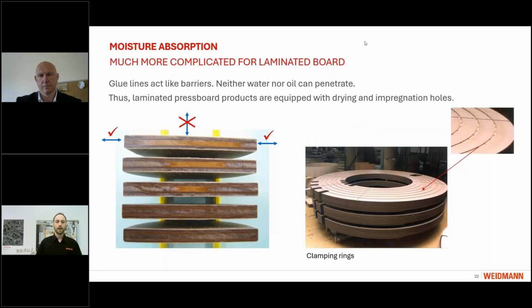Next, we have the glue lines. You know that Weidmann will produce laminated board if the thickness requirements get big. However, what is very crucial to know here is that these glue lines, especially the polyester ones, act as an oil and moisture barrier. You can see this nicely on the left-hand side, where the top picture has some whitish, brownish light coloring. And we see that this coloring can only be reduced from the sides, because from top and bottom there is a glue line, which means no water can penetrate through it.